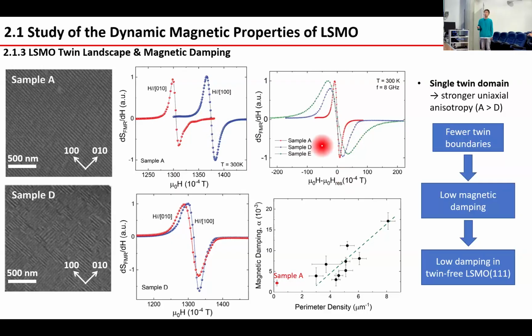And I also measure the resonance linewidth, where sample A shows a relatively narrower resonance linewidth than sample D. So it's indicating the dynamic magnetic damping is coming from the pinning effect from the twin boundaries. And so we also extract the magnetic damping on the series of samples, where sample A shows the minimum magnetic damping. And the magnetic damping also increases with the increase of the perimeter density, where the perimeter density is the density of the twin structure or network. So we can conclude that fewer twin boundaries could lead to lower magnetic damping. And one thing we can conclude is that if the LSMO grows in the 111 orientation, it could achieve a twin-free structure. So it could achieve low damping as well.